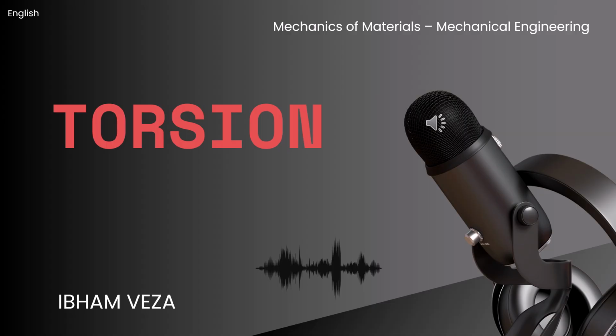What happens when you remove that big plastic torque Tp? Does it just spring back? It tries to spring back elastically. Imagine the stress distribution for Tp, uniform tau_y. Now imagine applying an opposite torque elastically that's equal in magnitude to Tp. The material recovers elastically based on that linear stress distribution we saw earlier. When you superimpose that elastic recovery stress, which varies linearly, onto the uniform plastic stress, they don't perfectly cancel out. You're left with residual stress.